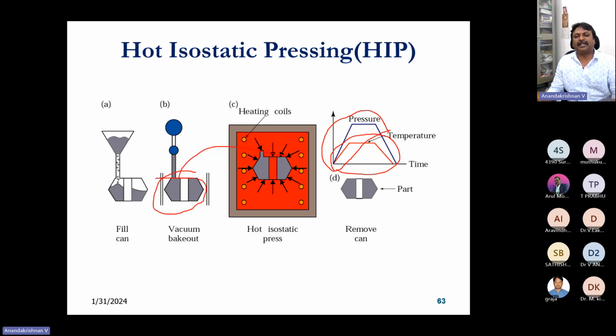So hot isostatic pressing. Here I want to mention one important point. The powder-based additive manufacturing components cannot be directly used, because I told you the particle sizes are different. Spreading of the powders can create some cavities. Layer to layer, there may be non-uniformity in the powder particle distribution. Under that condition, there will be some porosity. You cannot usually have 100% densified components.